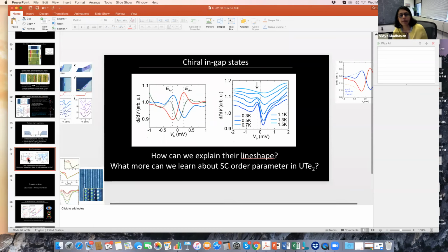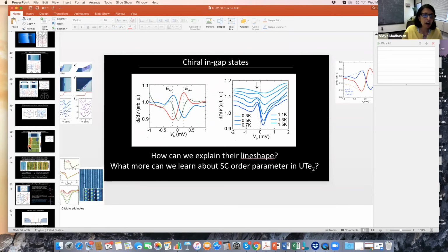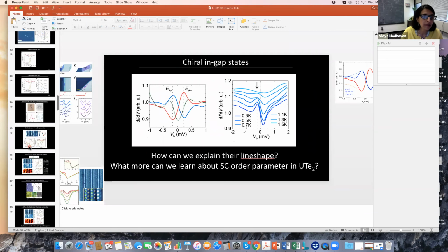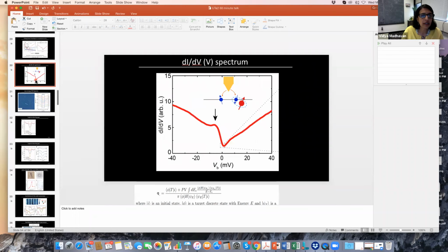But the thing is, there's a Kondo resonance at higher energies, remember? And that Kondo energy scale is pretty large. It's between 30 to 50 Kelvin. From our data, it's like 30 Kelvin, and the superconducting TC is 1.6 Kelvin. The superconducting gap energy scale is a few hundred microvolts. The Kondo energy scale is a few millivolts. So they're very well separated in energy. So below the Kondo temperature of 30 Kelvin, you can think of this as a metal. A heavy band, but still a metal.